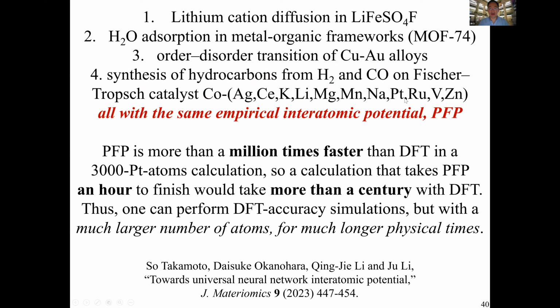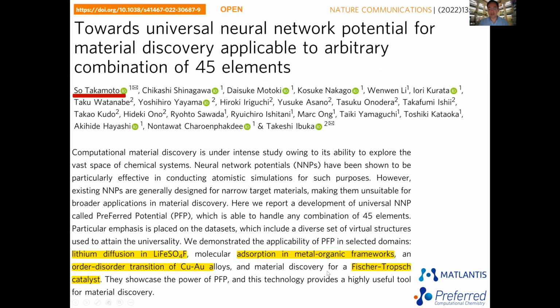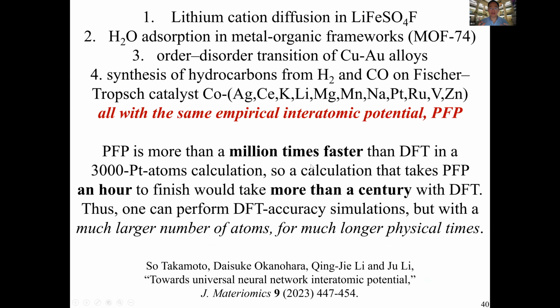So the point is that previously, we usually did one problem by developing a particular, let's say, neural network or machine learning potential. We publish a paper on that. So what this paper shows is that you can use the same potential with quite consistent errors across heterogeneous formations, and you can just arbitrarily do all these different chemistries. And generally, the error that we have is similar to TeaNet, on the order of half of the chemical accuracy, sometimes actually much better than that.